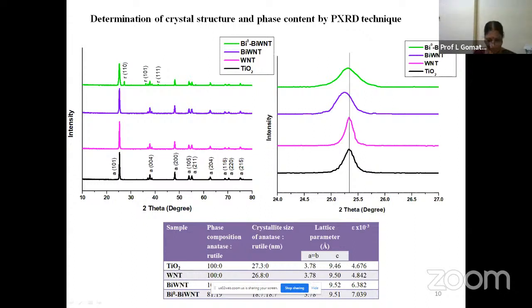Second, you can check that we have given a small table at the bottom where we have represented that TiO2 has only anatase structure, and WNT also has 100% anatase. BiWNT also has 100%, whereas Bi0 BiWNT is showing 81% anatase and 19% rutile structure in the compound. And we have represented the crystallite sizes also. As we move in the table from TiO2 to Bi0 BiWNT, the crystallite size keeps decreasing. Another important factor we are supposed to observe here is that both the anatase crystals and rutile crystals have the same crystallite size, 18.7 nanometers.